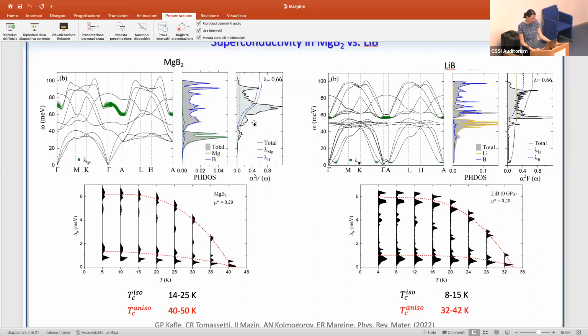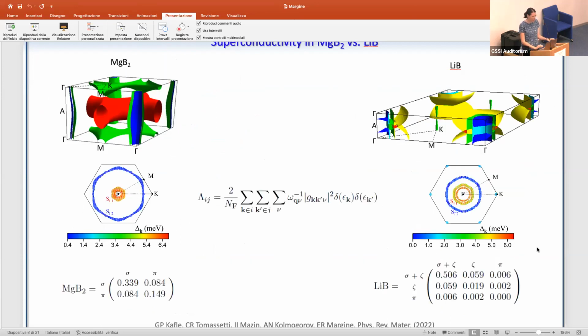One thing that I point out right now is that if we solve the anisotropic equation, you can see that we get a multi-gap structure that can be associated with different parts of the Fermi surface. The highest part comes mostly from the boron pi states, while the lower part comes from the nearly free electron states. So maybe this band-resolved analysis can give an even better idea of where the coupling comes from. This is what we plotted here, the band-resolved electron-phonon coupling. And again, we are comparing with MgB2. As expected, since we don't have the pi states, there is no contribution to lambda coming from the pi states.